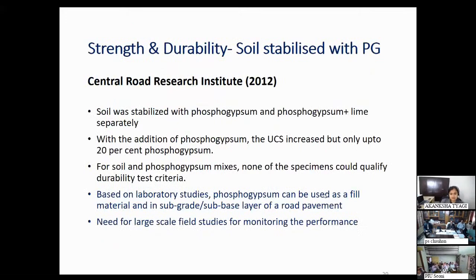The Central Road Research Institute of India also has published some of the results in its 2011-2012 report. But I couldn't see much of the published literature, although. In this study, they stabilized the soil with the phosphogypsum and phosphogypsum with lime separately. They found that with the addition of phosphogypsum, the UCS increased, but only up to 20% of the phosphogypsum. And after that, it decreased. So they defined this phosphogypsum percentage as 20%.